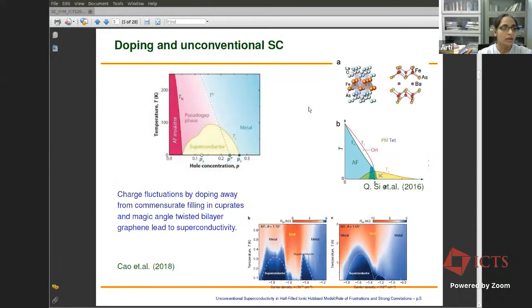Now, another common thing about all these materials is that the superconductivity appears when you dope the parent compound away from half filling, away from the commensurate filling. So for example, in cuprates, you have to dope it with oxygen, and as the hole concentration becomes sufficiently large, the system shows a transition from antiferromagnetic Mott insulator to superconductor, and the same thing happens in pnictides as well as in bilayer graphene.